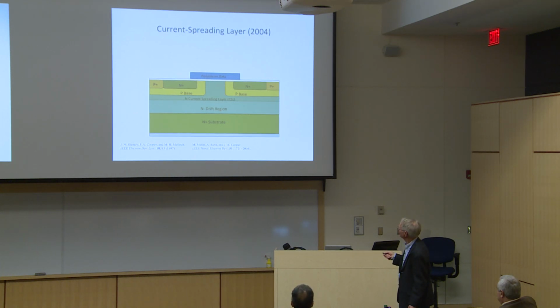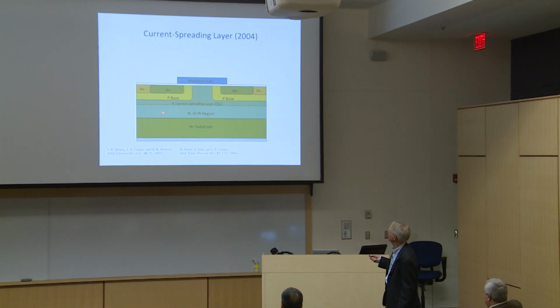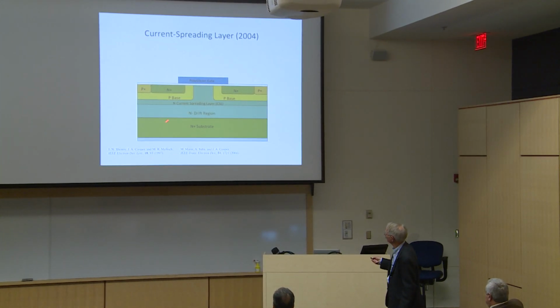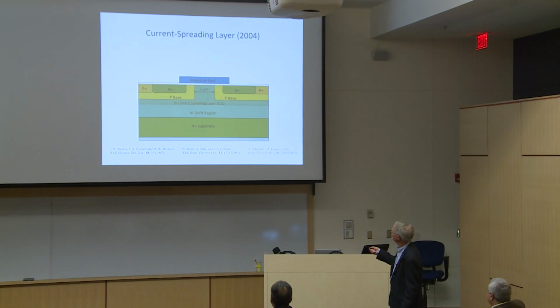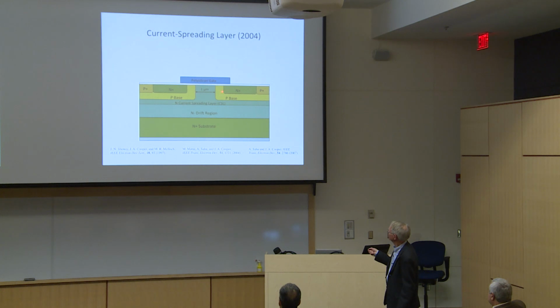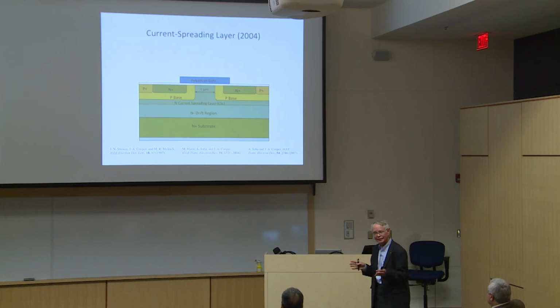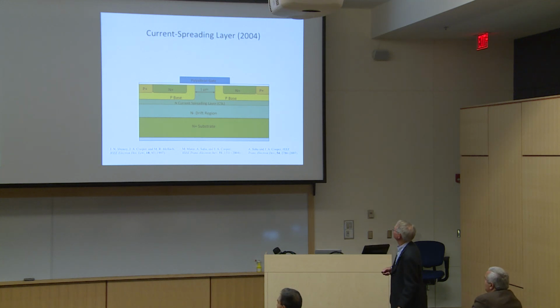So by making it more heavily doped, we do a couple of things. One is when the device is turned on, we have current flow that comes vertically, and then it has to spread into this region. Well, you get current crowding here, and that raises the resistance. So by putting this current spreading layer in, it alleviates some of that current crowding, and it reduces the resistance. Now, the other thing it does, it allows us to make this spacing here very small, because otherwise, those of you who are familiar with devices will know that this is basically a JFET. It's a p-n junction FET that can pinch off the current flow through here. And so by making this layer more heavily doped, we can reduce that spacing. And the whole idea is to save area. So we got both benefits from that.